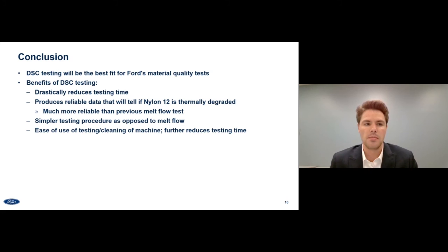And some of these benefits include significantly reducing the testing time. As stated previously, the melt flow machine took 45 minutes to completely run a test that included cleaning the machine. And the DSC will need minimal cleaning as opposed to melt flow machines, so Ford will be able to run multiple tests in very quick succession as opposed to very few tests with the melt flow machine.